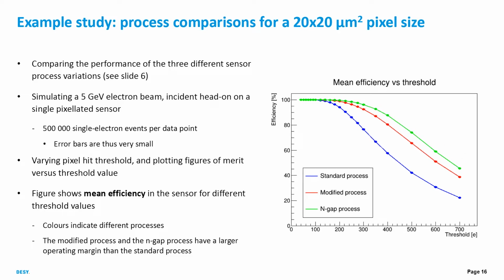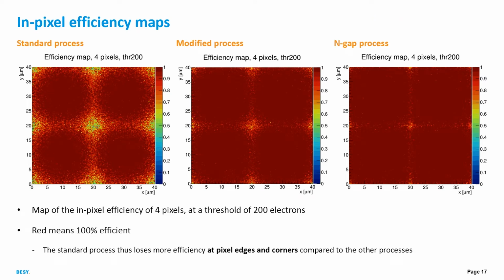Now we can also look, as I mentioned, at in-pixel efficiency maps. This shows the standard, modified, and NGAP process, with 4 pixels, so 1, 2, 3, 4, at a threshold of 200 electrons. Red here means 100% efficient, and blue means 0% efficient. What we can see here is that all of them are 100% efficient in the pixel centers, but at edges and corners, the standard process loses quite a lot of efficiency already at a threshold of 200 electrons. The modified process also loses some, and also the NGAP, but the NGAP loses the least.